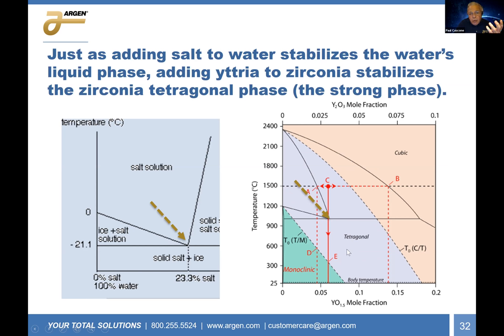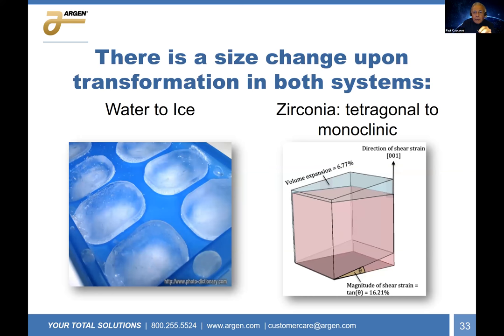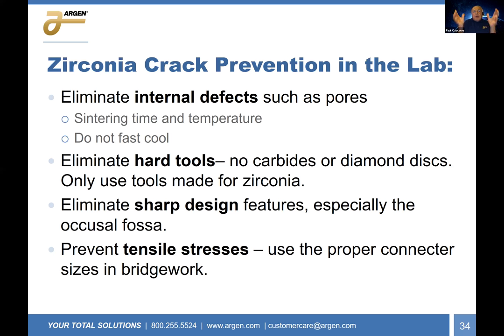But again, in this tetragonal form, the material has a lot of stress and strain, and any excuse for that material to release the stress, it will take. When it does transform, it increases in size, just like water will increase in size when you freeze the water in the refrigerator. In your freezer, the ice cube is about 9% larger than the volume of water you started off with. Here in the case of zirconia, the tetragonal to monoclinic form when it transforms will increase about 7%. So it literally tears itself apart. There's just no way of stopping that crack from happening. So for crack prevention in the laboratory, we talk about sintering, we talk about eliminating hard tools, we talk about design features, and we talk about preventing tensile stresses by using the proper connectors.